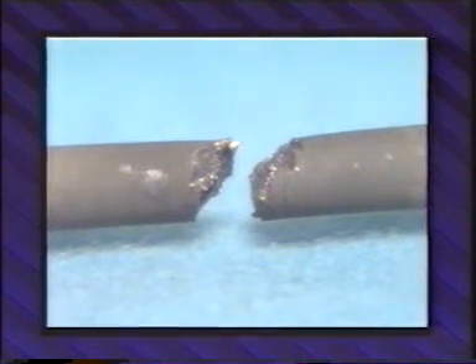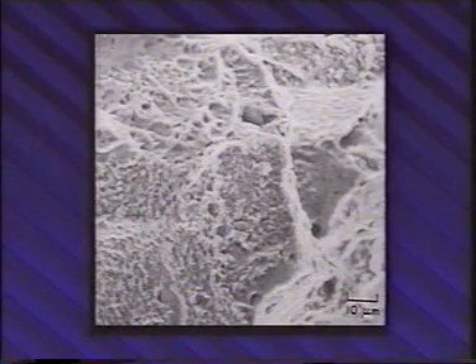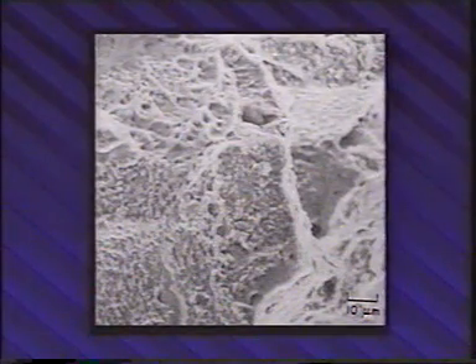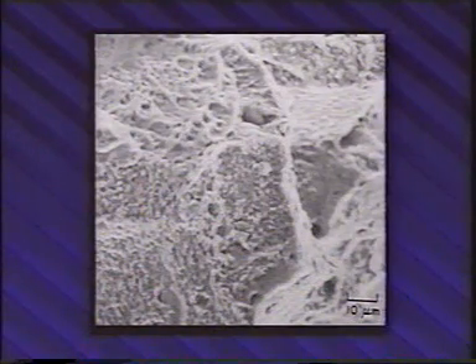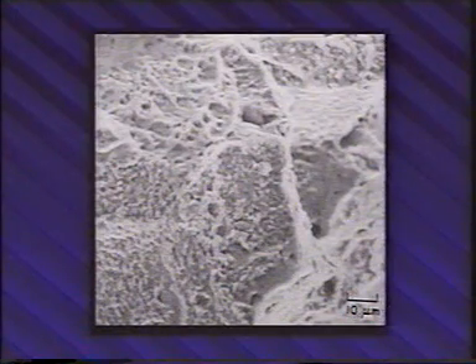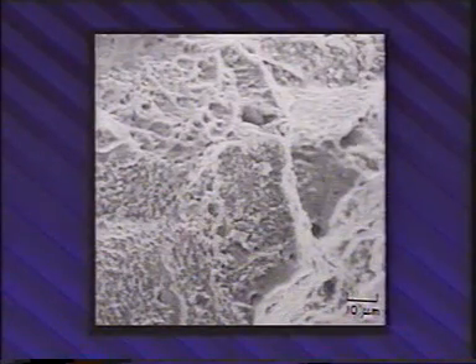The cracking mode is usually revealed in a polished longitudinal section. The cracking will frequently be seen below the fracture surface and parallel to the fracture surface. In fractographs, some stress rupture fractures exhibit both transgranular and intergranular fracture paths. In these instances, it is usually found that the transgranular fracture was initiated by a prior intergranular crack. The intergranular crack decreased the cross-sectional area and raised the stress. In general, brittle intergranular fractures are promoted by lower creep rates, longer rupture times, or higher temperatures.